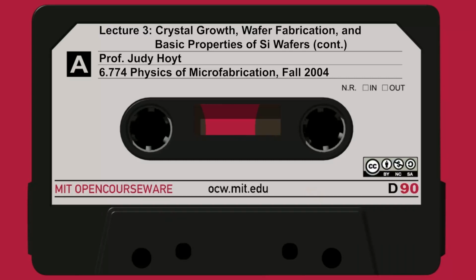So we take major organic contaminants like photoresist, and we typically remove them in a solution of sulfuric acid or oxygen plasma prior to doing any real refined cleaning like RCA clean. And then we remove trace organics with the RCA clean along with metals. So that's sort of the philosophy. And we'll talk about that next time.